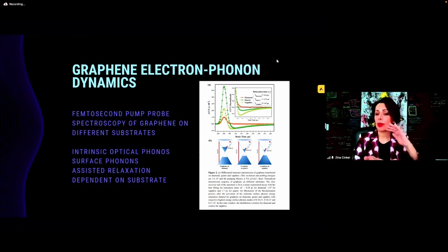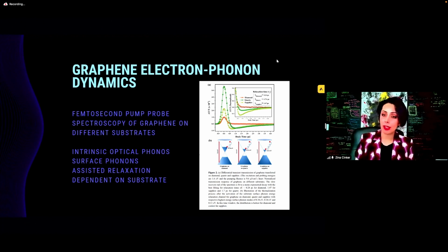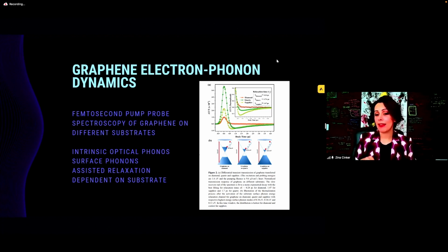What we did was that we had graphene on top of different substrates, and we studied that, and we found out that there is very strong coupling between the excited electrons of graphene and the phonons of the substrate itself. So one of the relaxation mechanisms that allows the electrons in graphene to relax much faster when it is on a substrate is through this coupling, using the surface phonons of the substrate.